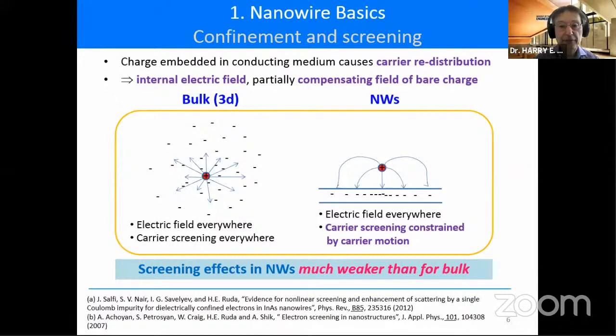The very last point I want to bring your attention to before I get into the talk, in terms of this background information, is screening. So screening is the idea that if we embed, for example, a positive test charge in a conducting medium, then the carriers in the medium around redistribute to screen off that charge, screen off its internal electric field by compensating the charge of that bare test charge. In 3D, you can collect charges from everywhere, and you can very efficiently screen that test charge, which means that the screening lengths are very short.